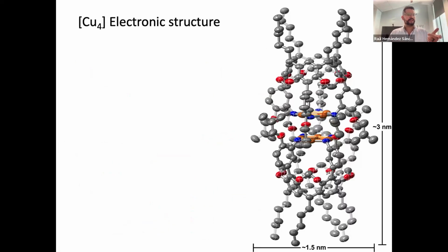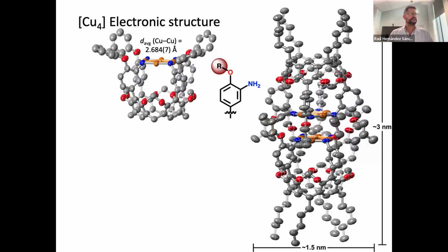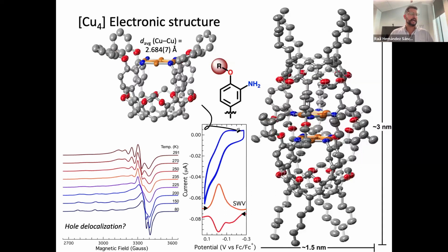Okay, so now what else did we learn about these molecules? Well, we learned that we can prevent dimerization if we change this particular R group. It's hard to see in the structure, but these are isobutyl groups appended to the ligand. If we change that to phenyl, then we have a compound that does not dimerize in the solid state, because now the group is fairly large. We know that it has an oxidative event just about 200 millivolts towards oxidative potentials. We can isolate that particular oxidized species and then start probing its EPR.